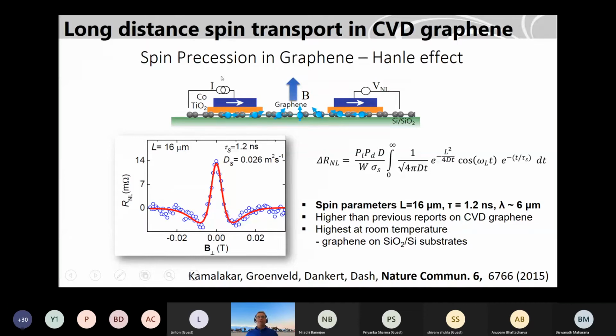As I told you in the last lecture with metal spintronics, you can apply a perpendicular magnetic field while doing these experiments, and spins will precess with the Larmor frequency. So you get these line shapes of the resistance with magnetic field. That is called Hanle spin precession. We also developed the spin diffusion equation, as you may remember from the last lecture. This is the diffusion part, this is the precession part, and this is the dephasing. We don't have any drift because we don't apply an electric field along the channel. The electric field is only in the left part.